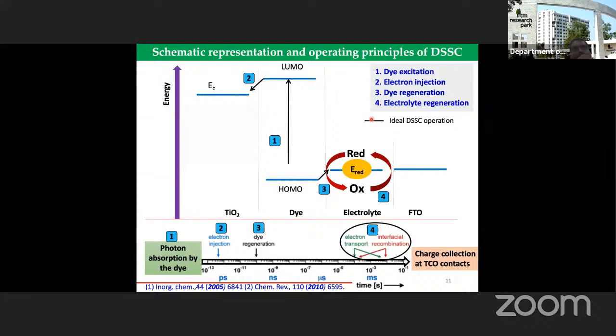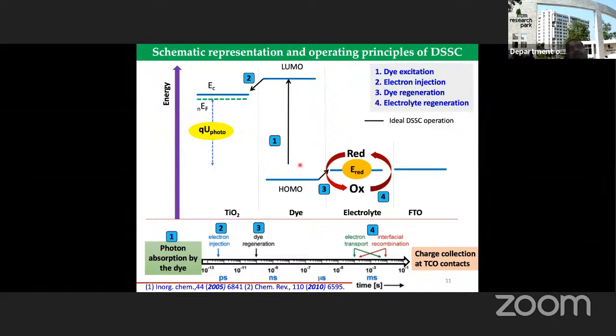But you have to be very careful. What is the voltage that we get out of this cell? It is from the Fermi level in the conduction band of TiO2 to the redox energy level of your electrolyte. From where to where? From the Fermi level in the conduction band to the redox energy level of your electrolyte. That decides what is the voltage of this cell. It is not the band gap of the dye that decides it.